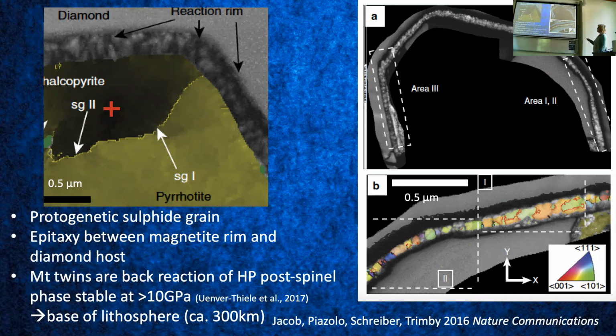And then the other finding was that we were going to look at this rim, which turned out to be a reaction rim. That proved quite difficult because the foil was still too thick. So we shipped the foil back to where it was cut, which in my case was in Potsdam in Germany, and I asked my colleague there to thin the foil so that we could start studying the rim. She put it back into the machine and ran the gallium ion beam over it. We did this in real time on Zoom, email and WhatsApp. She actually lost most of the innermost part when she cut it, which is always a danger. Fortunately, we had already analyzed it, and it didn't bother us that it was lost.